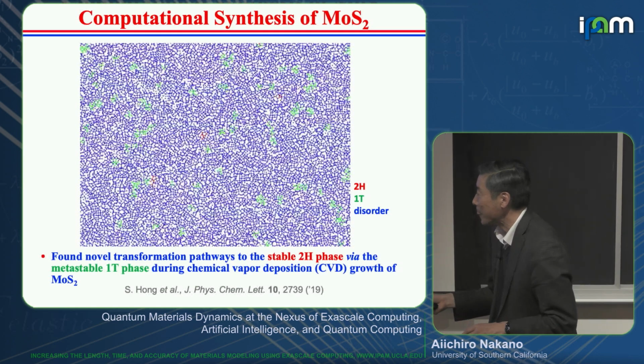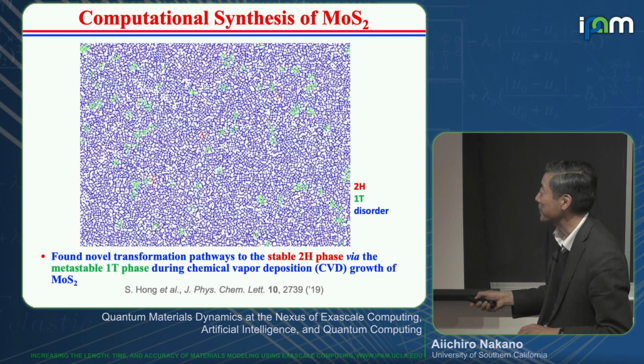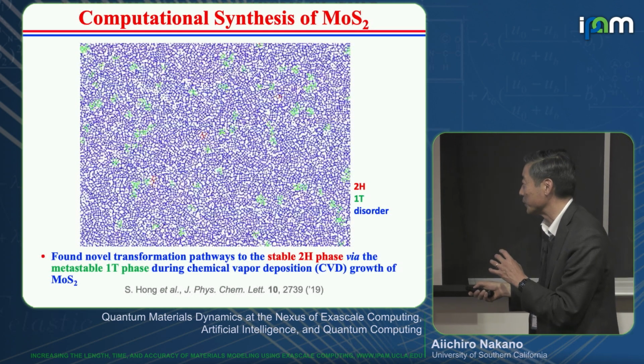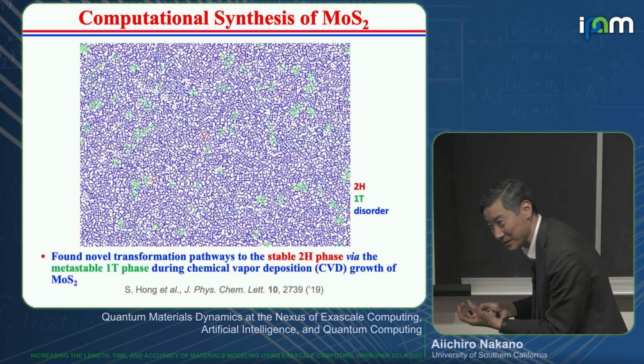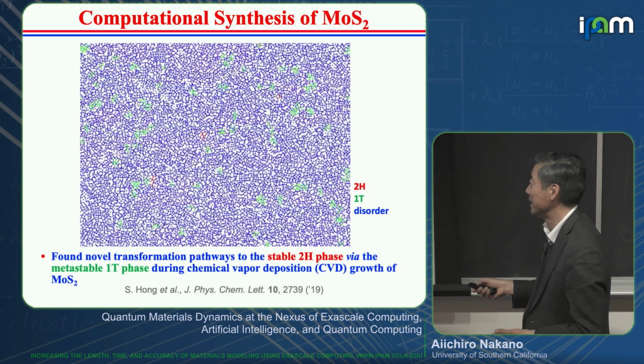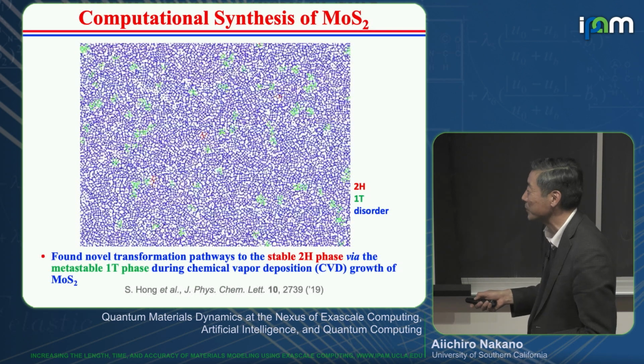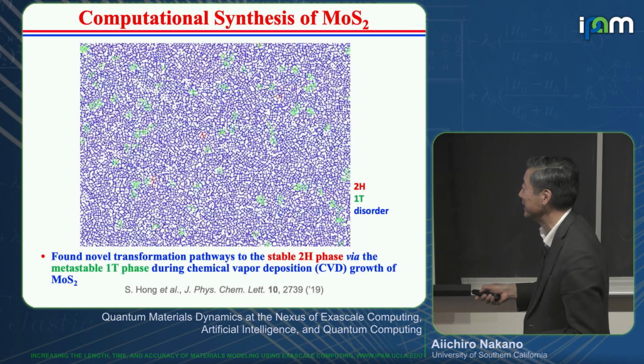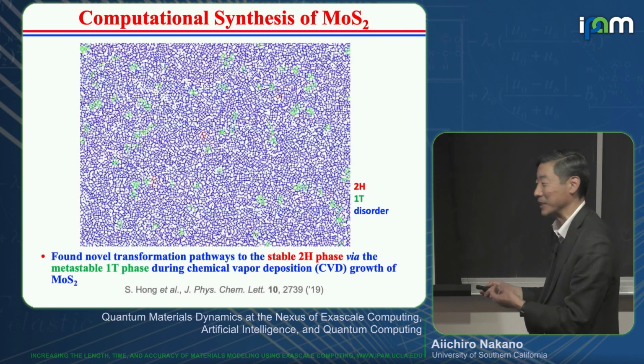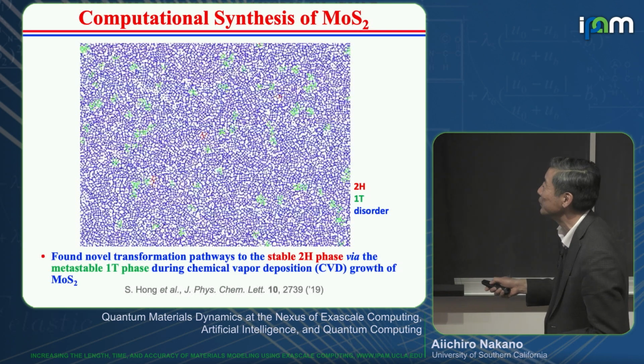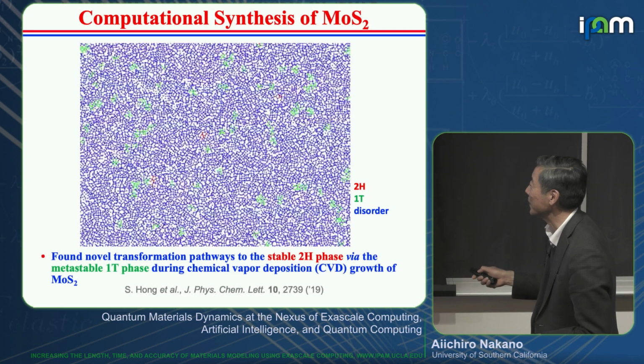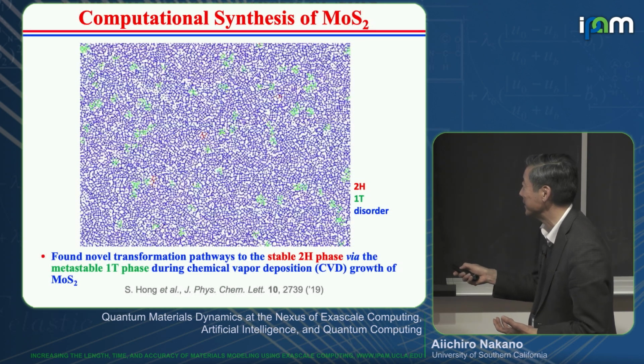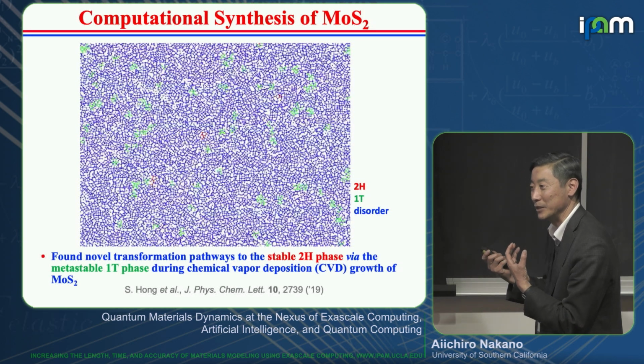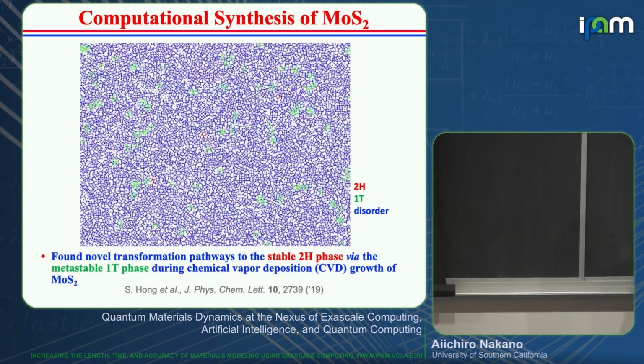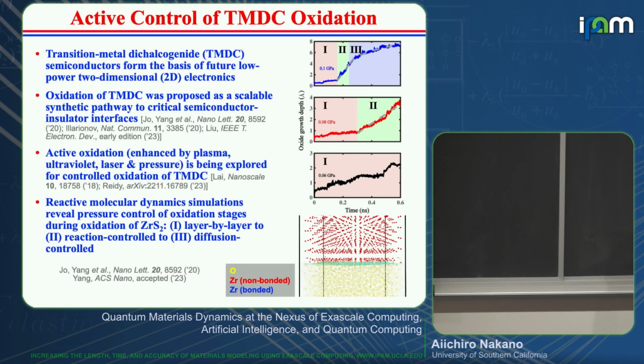Here, we found a very interesting transformation pathway to the stable 2H phase. The 2H phase is the global minimum, but it turned out, kinetically, a non-equilibrium path. It first goes to the metastable 1T phase during the CVD growth of MoS2, and then finally becomes the stable 2H. Here, blue is the disorder, 1T is the metastable 1T phase, and 2H is the eventual stable final product.